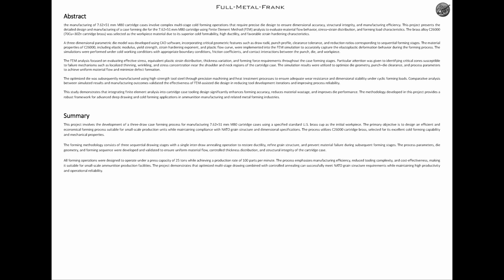The process utilizes C26000 cartridge brass, selected for its excellent cold forming capability and mechanical properties. The forming methodology consists of 3 sequential drawing stages with a single inter-draw annealing operation to restore ductility, refine grain structure, and prevent material failure during subsequent forming stages. The process parameters, die geometry, and forming sequence were developed and validated to ensure uniform material flow, controlled thickness distribution, and structural integrity of the cartridge case.